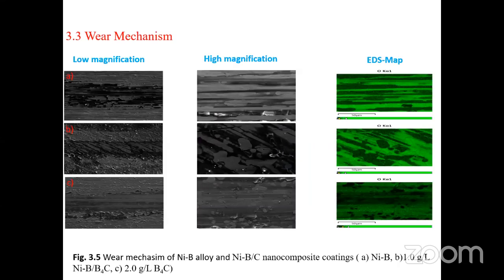Wear mechanism. Figure 3.5 shows the wear mechanism of nickel boron alloy and nickel boron, boron carbide nanocomposite coatings: A nickel boron alloy coating, B 1 gram per liter boron carbide addition, and C 2 gram per liter boron carbide addition. According to the image, in the nickel boron alloy coating the predominant wear type was abrasive wear, while delamination was seen as the predominant wear type with the addition of nanoparticles. The reason for that is the formation of micro cracks on the surface due to high temperature and fatigue that occur during the wear, and these cracks progress under the surface and break apart.